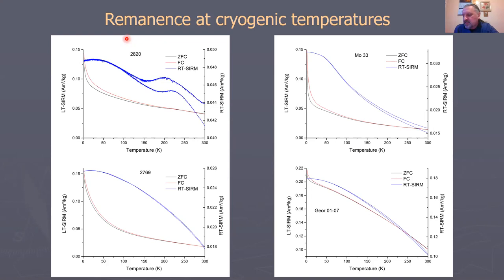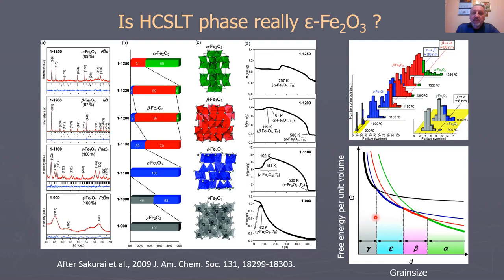And so epsilon iron oxide, as it is known in material science, is a peculiar polymorphic form of iron 3 oxide, which crystallizes in the orthorhombic crystal lattice. Its interest in magnetic material science stems from the fact that it has a huge coercive force at room temperature, exceeding 2 Teslas in the most perfect samples.